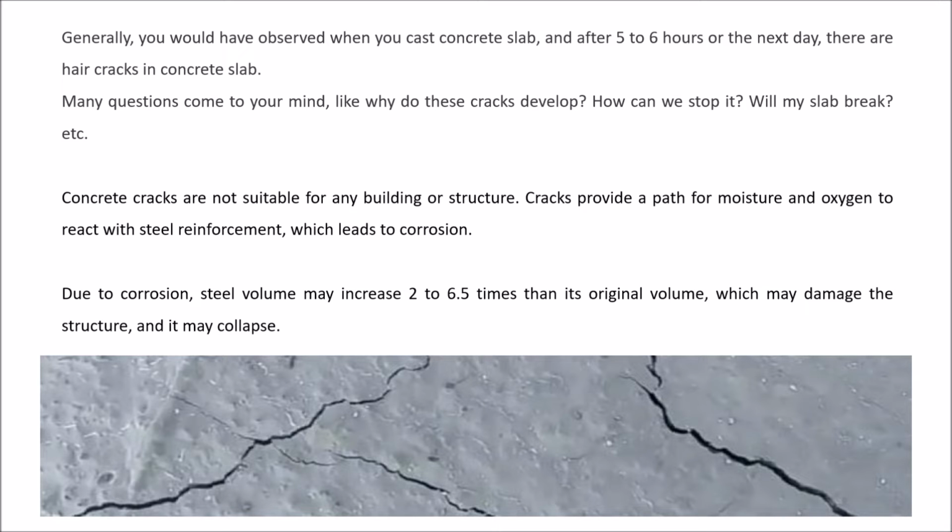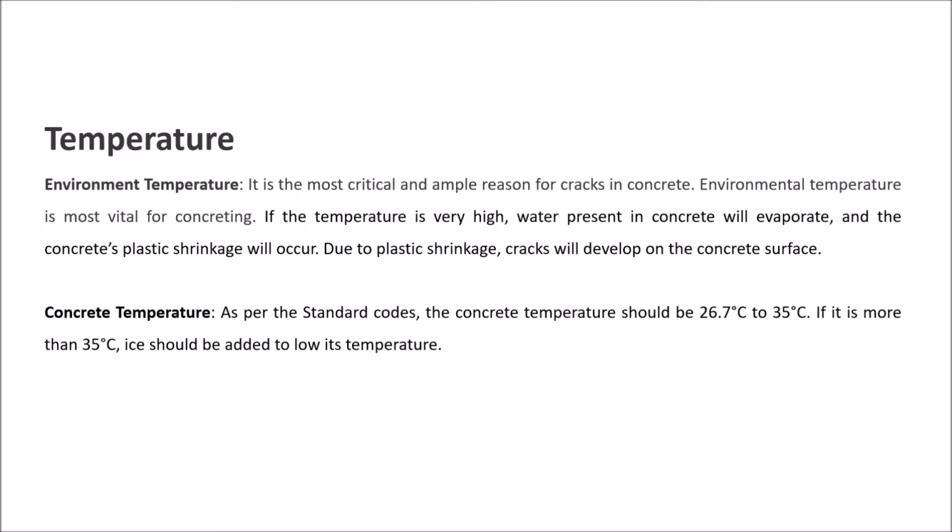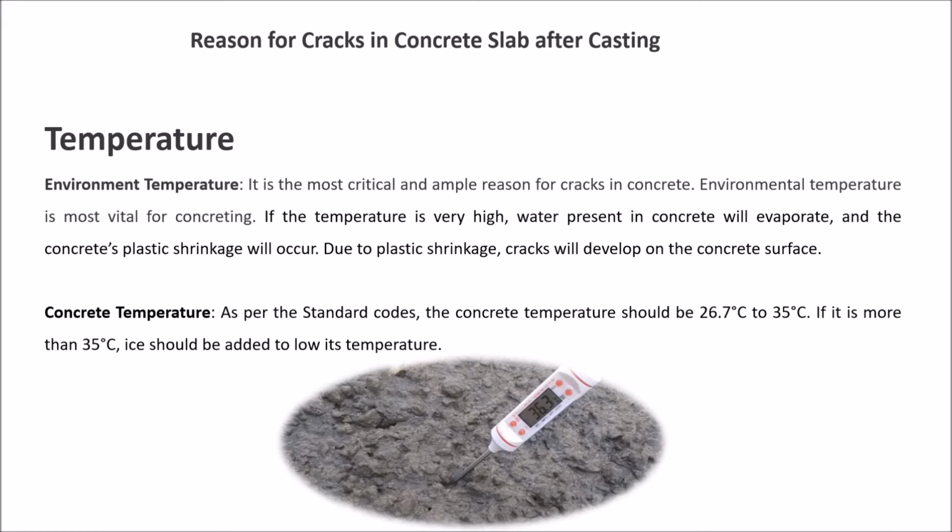The reason for cracks in a concrete slab after casting, first, is the environment temperature. It is the most critical reason for cracks in concrete. If the temperature is very high, water present in concrete will evaporate and plastic shrinkage will occur. Due to this shrinkage, cracks will occur on the concrete surface. As per the Indian standard codes, the temperature should be 26 to 35 degrees. If it is more than this, then we can use ice so that the temperature in the concrete can be lowered.